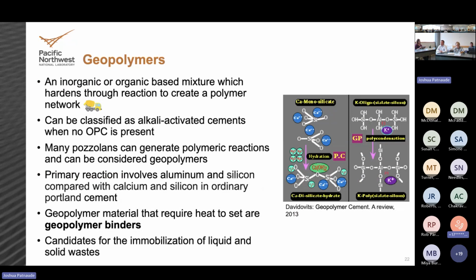And there's a quick note, I mentioned geopolymers early. The difference between geopolymers and a traditional hydraulic cement is that in cement and growing the hydration products, you get dissolution and then precipitation of mineral phases that start to link up. At its core, what a geopolymer does is you use something like a metakaolin product. It still has calcium and silicon and aluminum in it. But in this case, instead of growing minerals, what you do is you start to get polymerization, where the various silicon atoms start to link up with one another and bond together, and you end up making a solid mass.